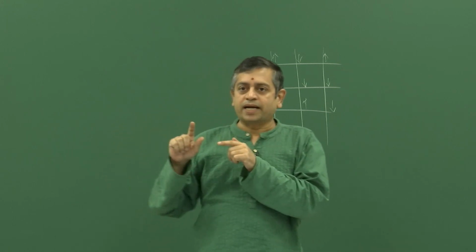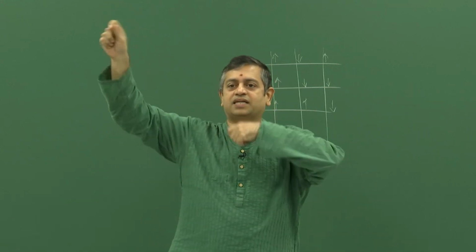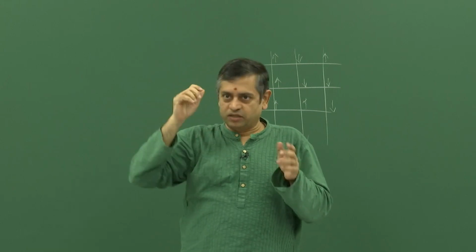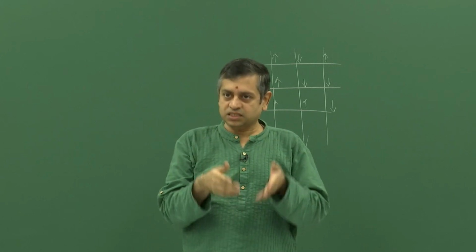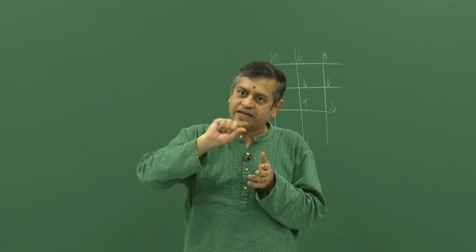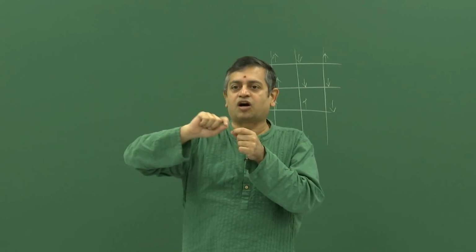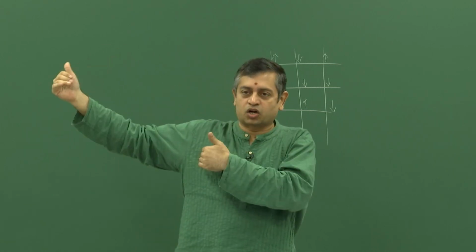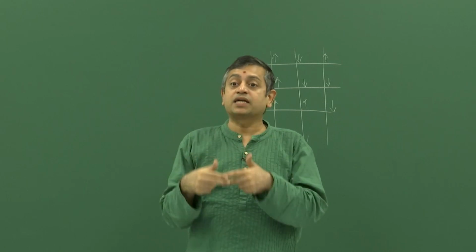Yeah, to do that, there are two things. You can't take random atoms and move them and then expect that kinetics will come out right. You have to use physically meaningful processes. What I am going to show tomorrow is vacancy kinetics. We introduce a vacancy, we make the vacancy hop, and we take the frequency of vacancy hops into account in calculating the time. That is one part. The second part is in the algorithm.